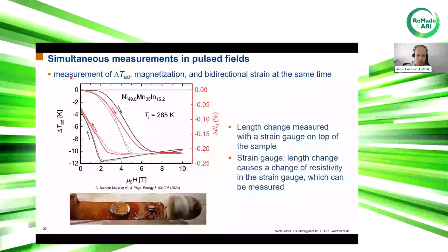Now to go back to simultaneous measurements in the pulse fields. Here I want to present simultaneous measurements of the magnetocaloric effect together with a bidirectional strain. You can see the sandwich type sample preparation, and on top of the sample there is a strain gauge glued to measure the length change by application of magnetic fields. In this strain gauge, you usually measure a change of the resistivity, and this can be related in the end to a relative length change, delta L over L0, of the sample.